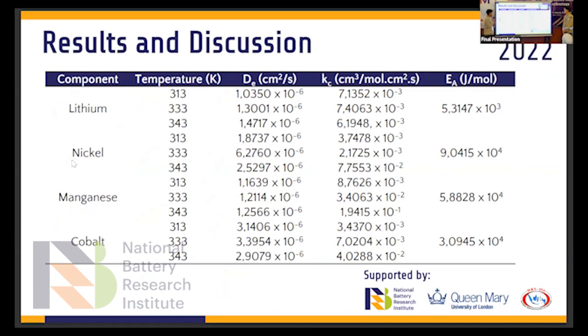And then the design parameters from the simulation are in this table, and the diffusivity of each component increases with increasing temperature, except at 70 degrees Celsius for nickel and cobalt. This phenomenon also occurs in the reaction rate constant parameter. This deviation can happen at 70 degrees Celsius because the hydrogen peroxide is decomposed.